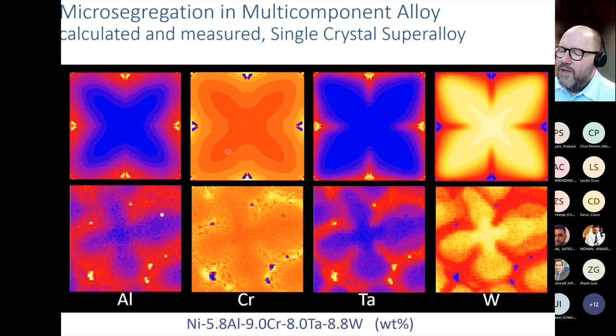We also find that chromium enriches in the liquid initially and then gets rejected very heavily by the gamma prime. So we have the maximum chromium concentration here and the minimum close to that inside the gamma prime phase. We find the same pattern in the experiment as well. And then finally, we've got tungsten. Tungsten segregates towards the dendrite, the gamma phase initially, so it enriches in the dendrite core and keeps depleting, and then gamma prime nucleates and doesn't dissolve any tungsten either. So that rejects it even further, and we see that represented in both the simulation and the experiment. So we're actually quite happy with the agreement there and confident that at least for this type of alloys, we can do these calculations for a fairly complex alloy.